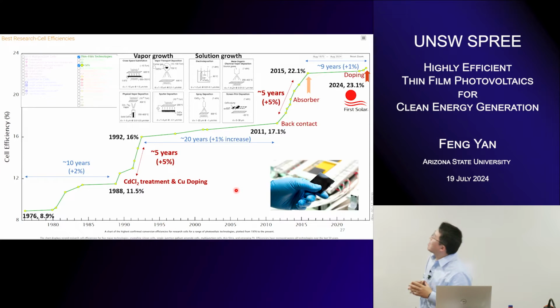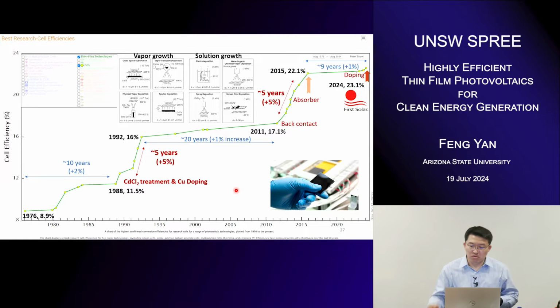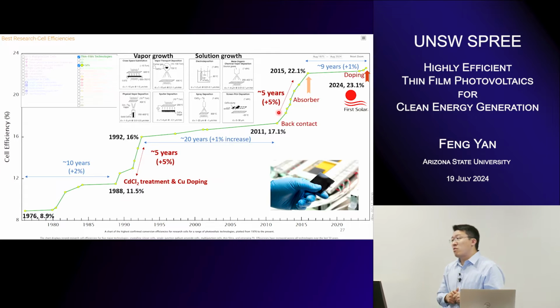Since 2011, they demonstrated around 17%, and First Solar, one of the major companies working on this technique in the world, introduced a lot of investment and boosted the efficiency from 17% to 22% within 5 years, which is very promising, and a lot of new ideas and innovations were introduced. But you can see it's stuck at around 22% since 2015, almost 10 years. But this morning, they released a new record, 23.1%. So this is very promising, with a lot of new techniques introduced. Today I hope to share a little about my learning experience working in this area for more than 10 years, how we can further engineer the efficiency and see how we can break this efficiency barrier.